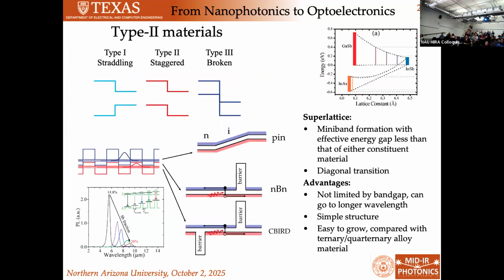But I want to talk about how we can leverage these plasmonic materials for optoelectronic applications. One of the reasons why the mid-IR is so fun to work in is that we have a lot of control over the optical transitions at these wavelengths. We can design what are known as type 2 superlattices. These are alternating layers of different semiconductors that create a superlattice, and we can engineer these to give us mini bands, and we can control the spacing between the mini bands so that we get an effective valence band and an effective conduction band, and we can control where that transition is.